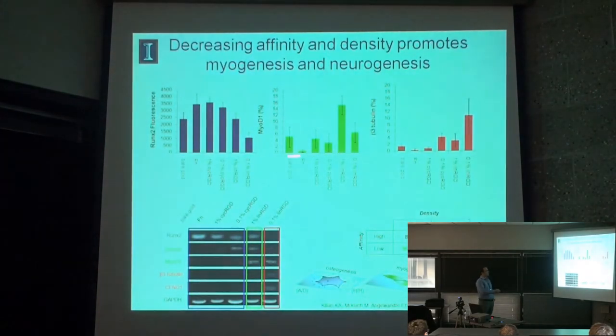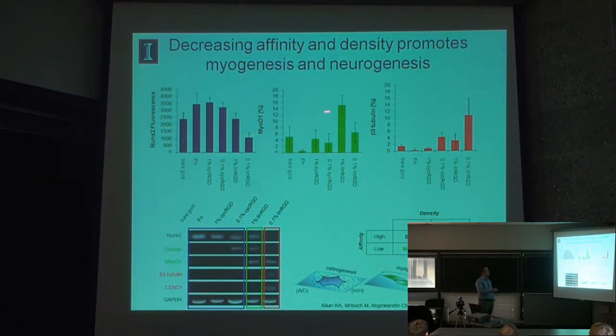So this is that quantitated, where here you see it's not an incredibly high amount, but it is significant. Here's the RUNX2 data showing that you get preferential bone marker expression, and then the MyoD on the high-density linear peptide, and beta-3 tubulin on the low-density linear peptide. We did RT-PCR of this as well, and we see the same sort of trends when we look at the gene expression level. And so we see higher expression of muscle markers and neuronal markers on these linear peptides.